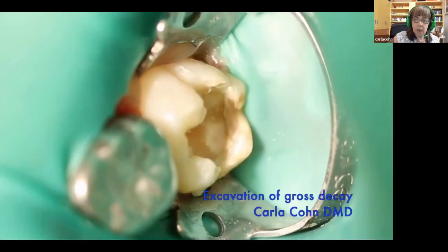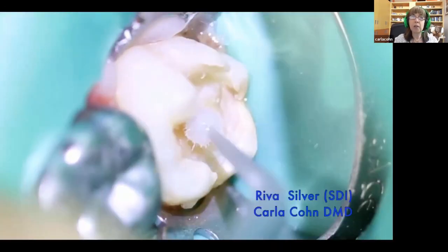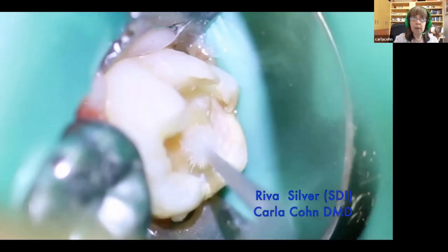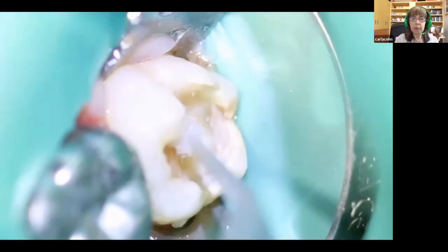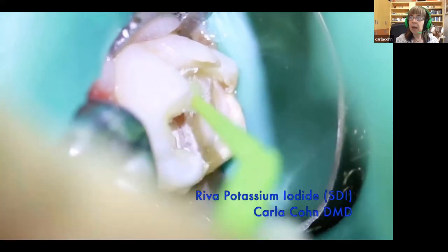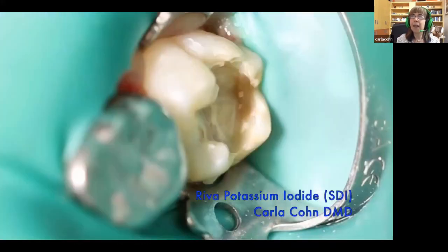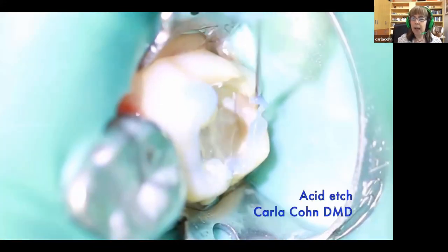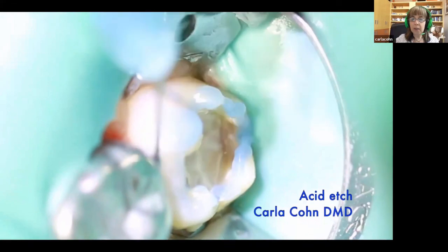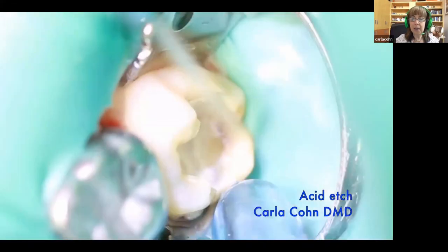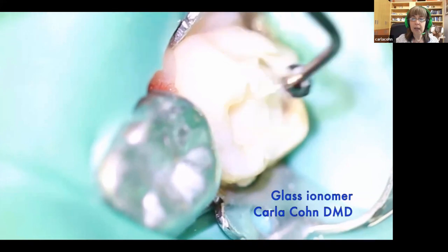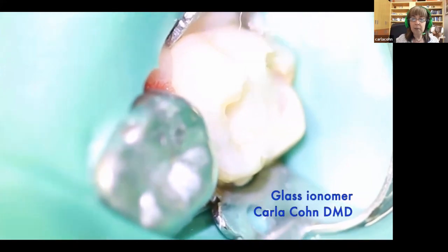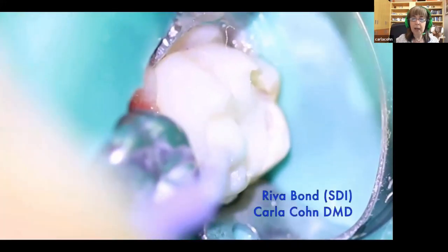So in our co-cure technique, a second case, excavation of gross decay, placement of our Riva silver, and then our potassium iodide to minimize that stain, 90 seconds. I've speeded it up for you. We can put our acid etch on at this point. It's a good idea to do double duty, because I do want to rinse that potassium after it's been placed. Pure glass ionomer, Riva bond, and then the Luna composite.